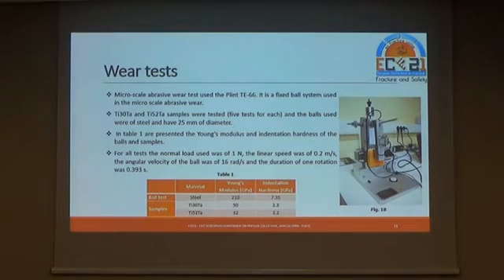Microscale abrasive wear tests use the Plint TE66. It is a fixed ball system for microscale abrasion. Titanium 30% tantalum and titanium 52% tantalum samples were tested, and the balls used were steel, with 25 millimeters of diameter. Table 1 presents the Young's modulus and the indentation hardness of the balls and the samples.